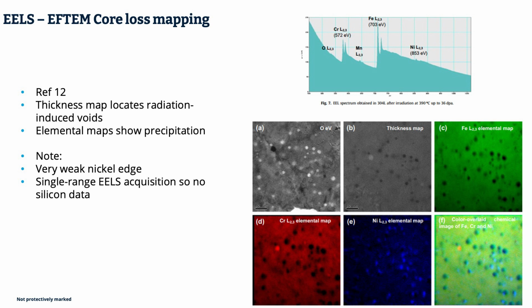One of the other perennial problems with EELS and looking at structural materials is the fact that the relative intensity of these edges also changes. And nickel is a particularly inefficiently excited edge. And consequently, despite the fact there's 10% nickel present in this steel, that's a miserably unimpressive edge.